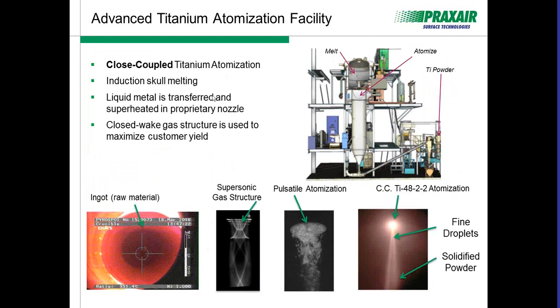When we look then at our new facility, we really want to draw attention to that we operate a close-coupled titanium atomizer. Again, as I said, we practice the industry standard of induction skull melting. So that's using that water-cooled copper crucible. And this is a video down here that I hope will play so that you can see as we lower in our material, which in this case was a pre-alloyed ingot, it's melted in this water-cooled copper crucible.